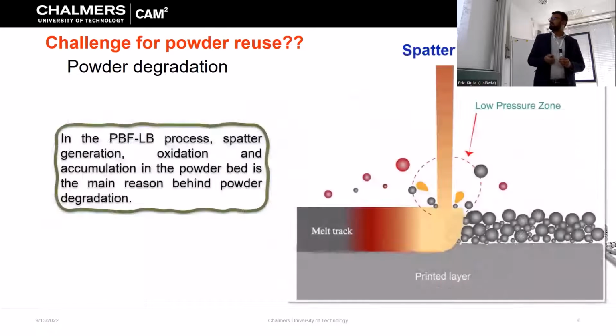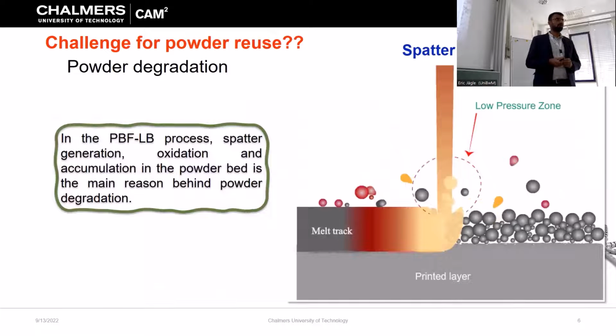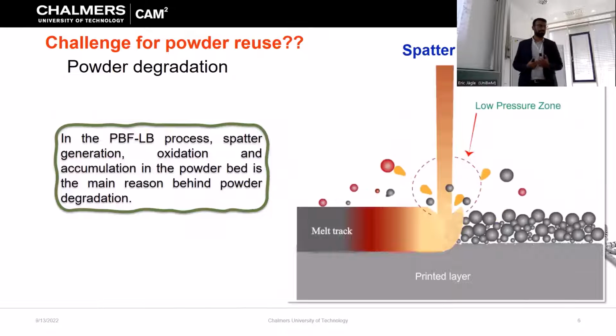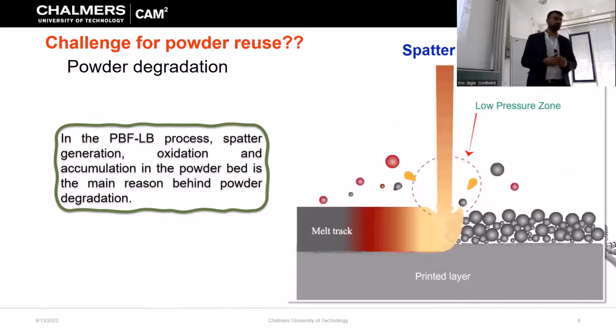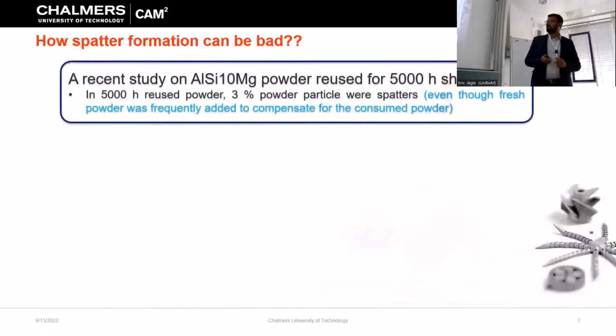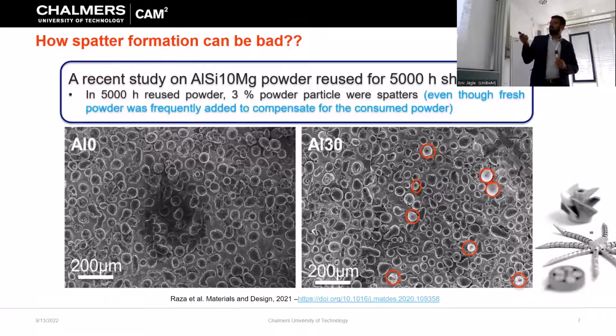And second is spatter formation, which is very common in laser. It is the main criminal, you can say, in powder degradation when it comes to the laser powder bed fusion process. And why am I saying that? Well, it was proved in our study on aluminum, silicon, and magnesium, where we reused this powder after 5,000 machine hours. And what we saw is that some spatters, these bright particles, appeared after reuse, and their number reached around 3% after 5,000 machine hours.